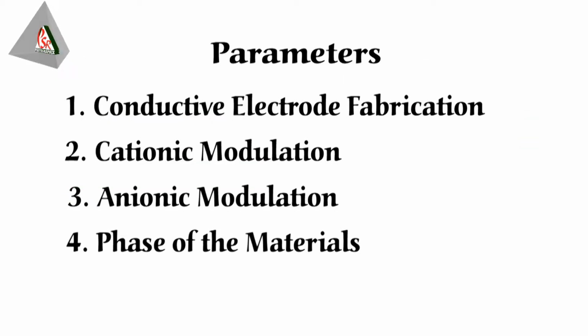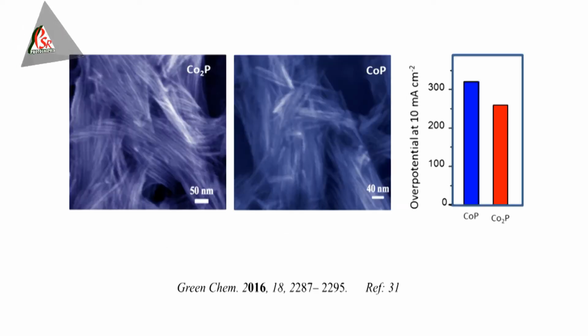Phase of the material: metal-rich phases show more activity as the conductivity of the metal-rich phases is high. A direct comparison between monocobalt phosphide and dicobalt phosphide reveals dicobalt phosphide has much higher activity.